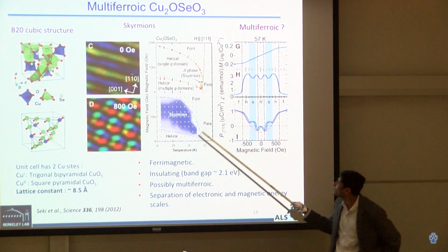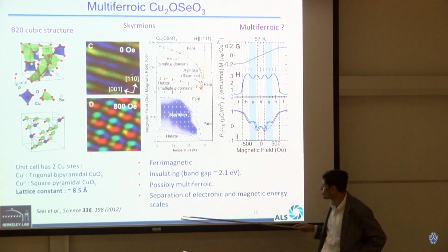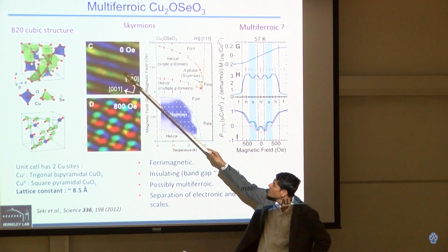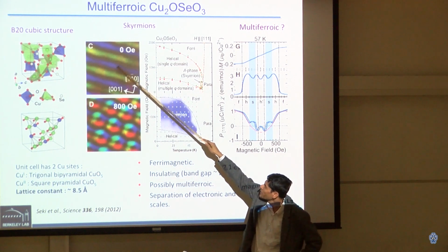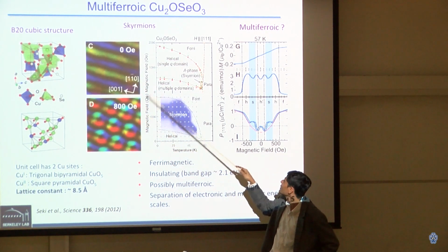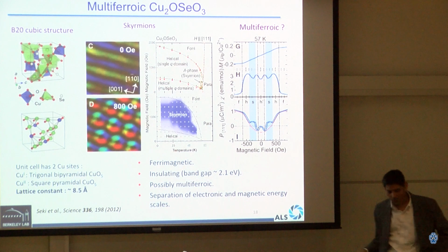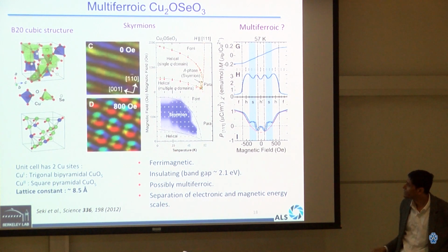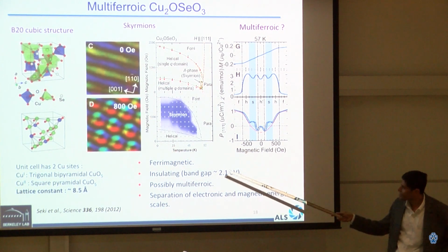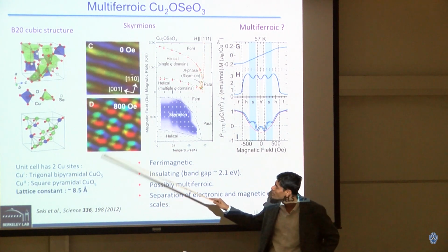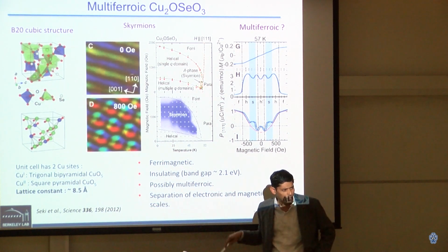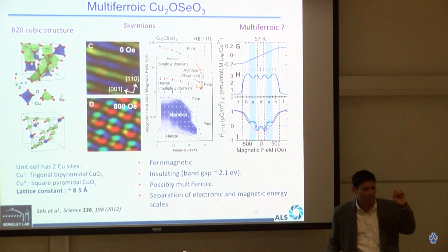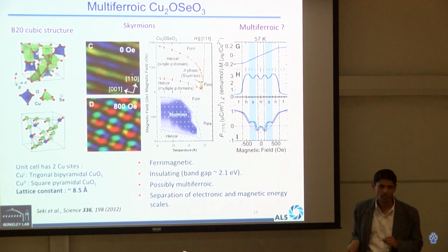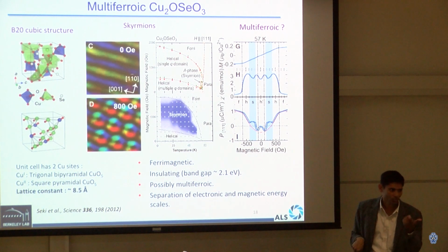But before even that, just to show you, this is not our work, it is from Tokura's work in Science, where he finds that there are helical states and there are skyrmion states, very similar to manganese silicide. This caught our attention because we now knew that for this material we can access the structural Bragg peak 001, which we could not do for manganese silicide, whose lattice parameter is only 5 angstrom. So we could not access that.